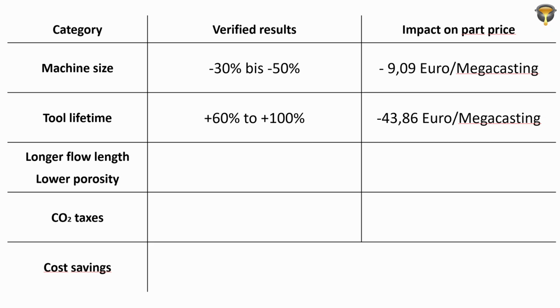But the big savings, and here we now have a total cost of ownership view on the situation, is basically by extending the tool lifetime. The tool life is super critical in these large castings. So you have to go very quickly into the casting and have 50, 60, 80 kilograms of liquid metal rushing through that ingate, going to the end of the filling. That is a very high thermal stress. That is a lot of erosion from that flowing metal. And the tools are highly expensive. So changing them all the time, having a new PPAP done all the time, that adds up very quickly.